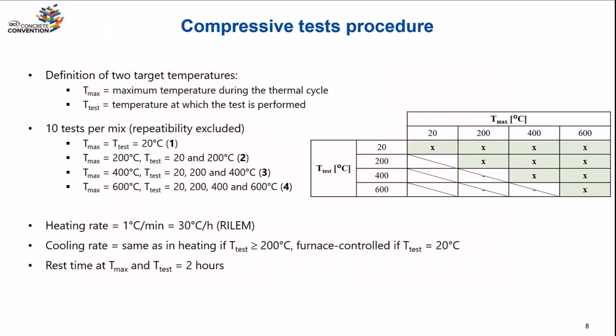So next experiments dealt with compression tests, compression strengths. So here, the test protocol that we devised included defining two important temperatures for concrete cylinders. The temperature Tmax is the maximum temperature that we will reach during the heating of the specimen. And then the temperature T-test is the temperature at which the test is performed.